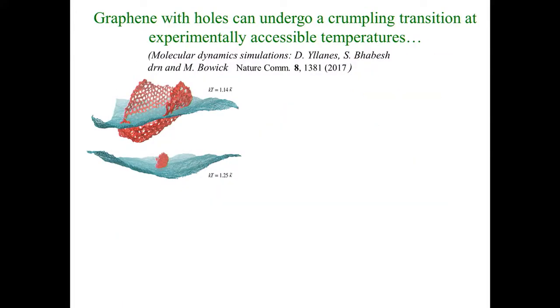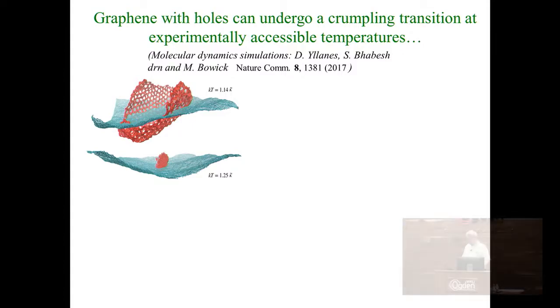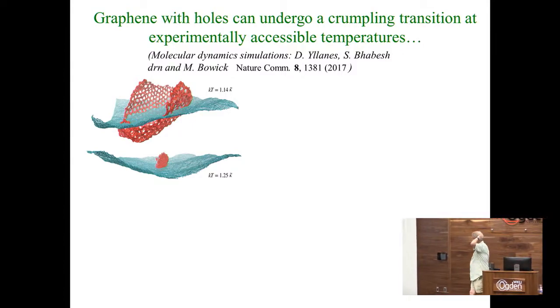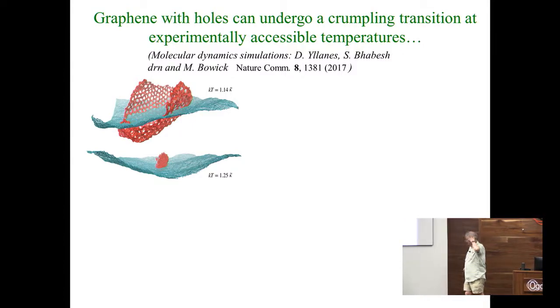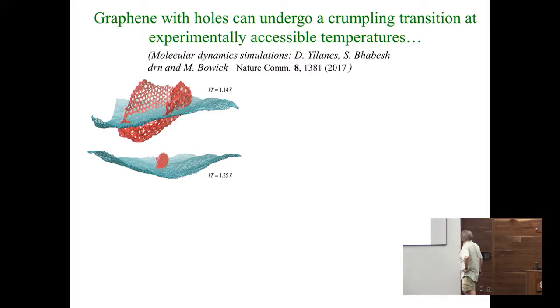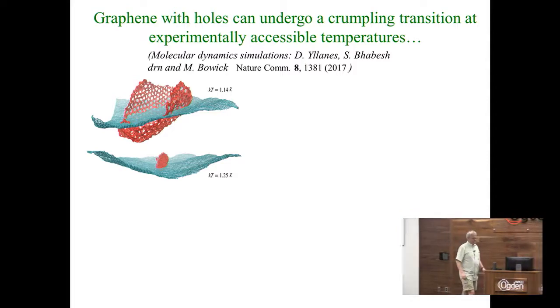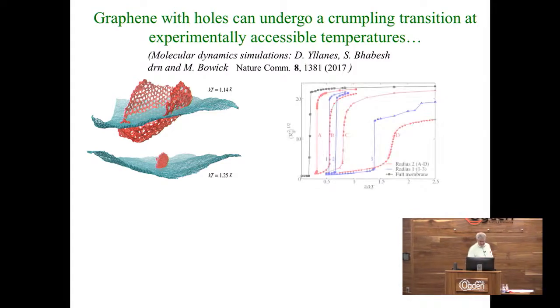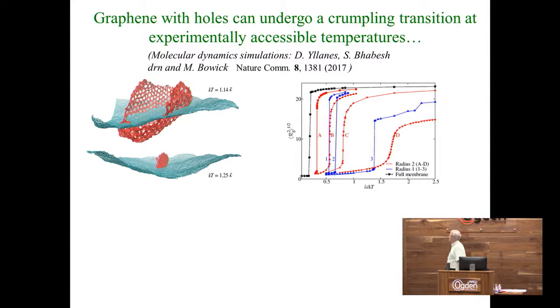So we went back, and as per the question we had earlier, we considered what would happen if we punched a lattice of holes in the graphene. Soften it up a little bit, make it a little more flexible. And so this is perforated graphene. It has a very interesting topology, of course. I want to argue that this does have a crumpling transition in an experimentally accessible range.